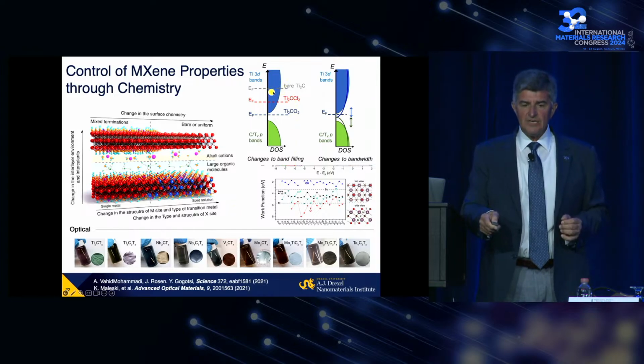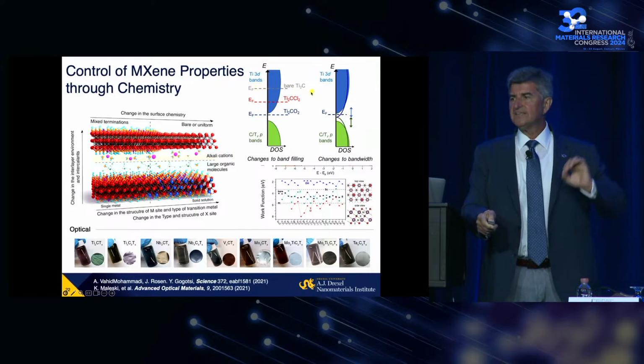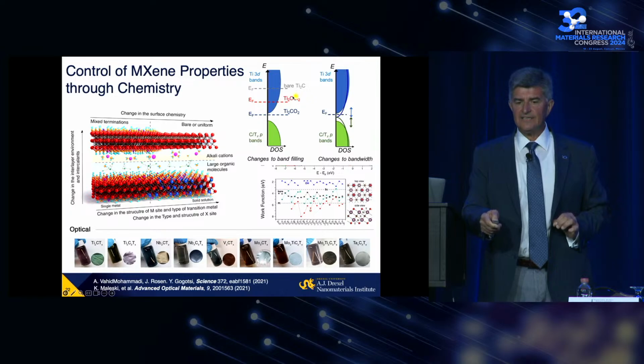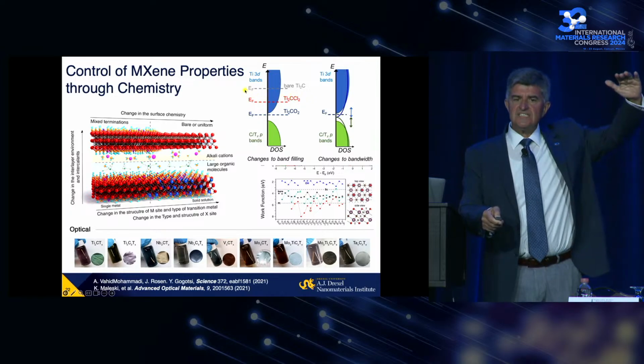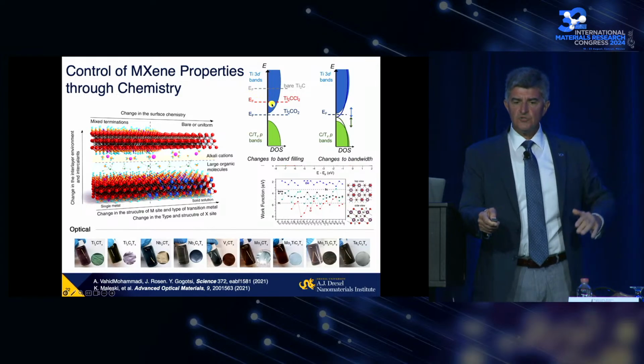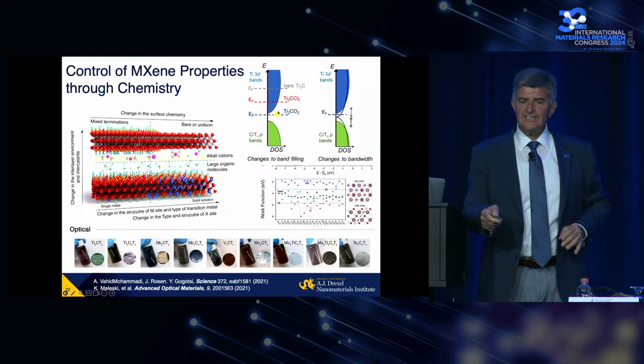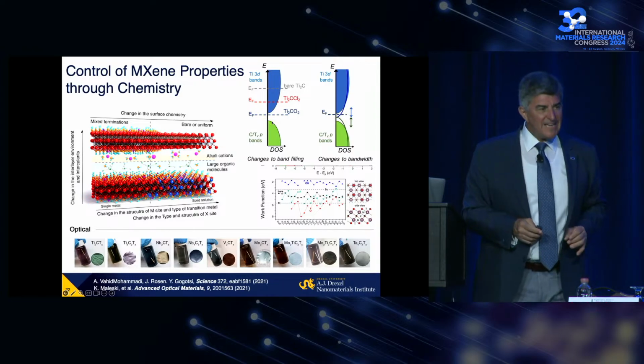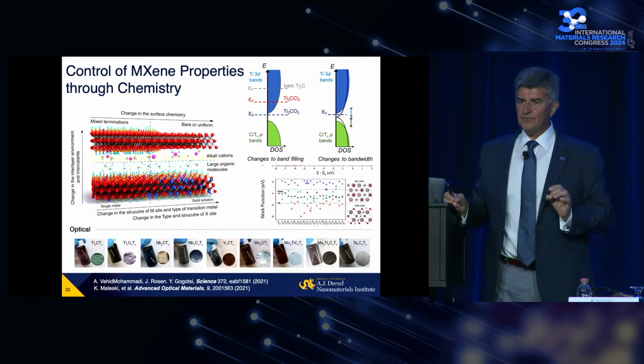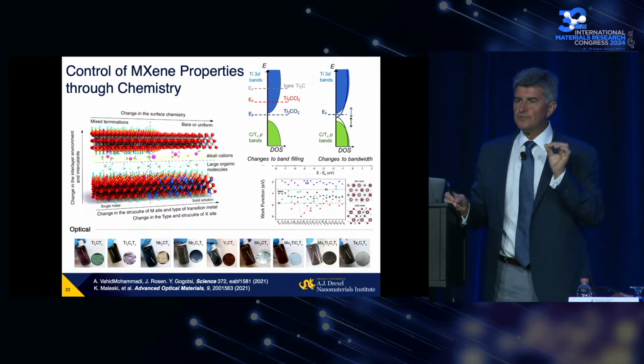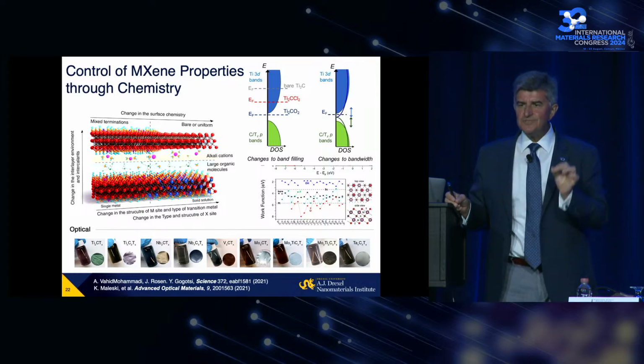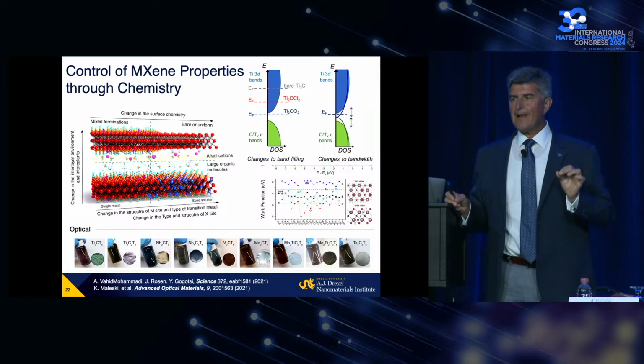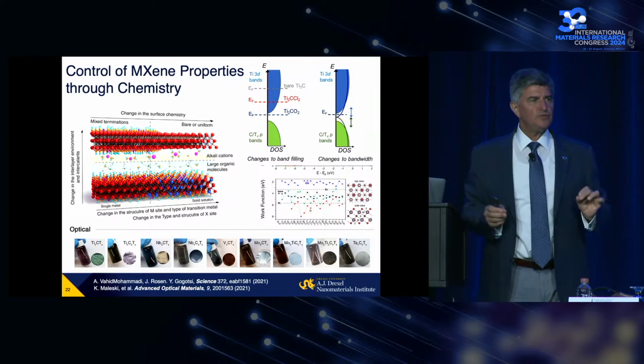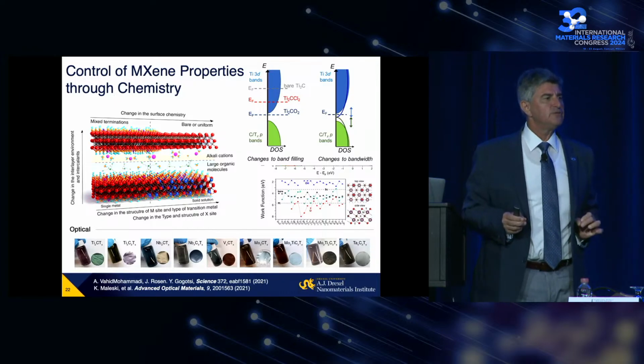For example, I mentioned MXenes have a high density of states at the Fermi level. All bare carbides and nitrides will be metallic conductors, but the density of states is not as high as, say, in copper or gold. So by changing surface termination, you can change the density of states and even open the band gap. So we basically have metals which are tunable, properties of which can be modulated during use like in semiconductors. The entire electronic industry is built on using semiconductors because we can modulate their properties.